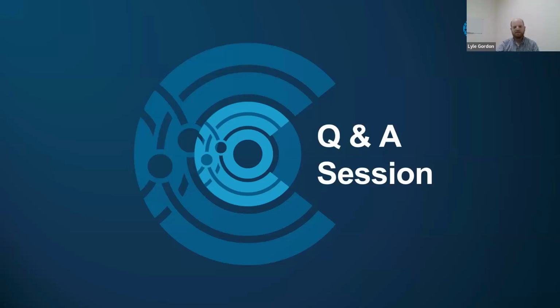There's a good XPS question I see. Sure. Why don't you grab that one? Someone is asking about measuring thickness of thin films by XPS, and they're also interested if you can do it by sputtering surface layers. This is something we didn't really talk about, so a nice segue into that. But yes, you can measure films either using XPS or other sputtering techniques like TOF-SIMS, where you incrementally remove the film by etching or sputtering, typically with argon atoms. And then you can remove surface layers. If you've calibrated that sputtering rate, then you can accurately measure the thickness of surface layers. And we do that routinely using XPS.